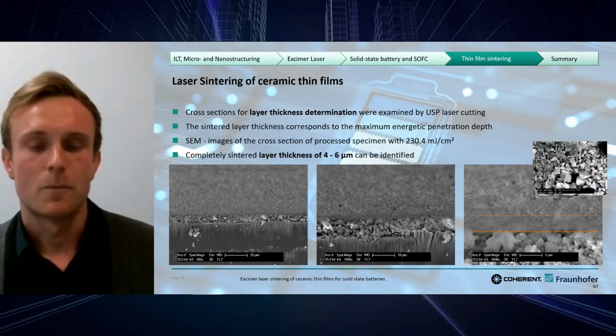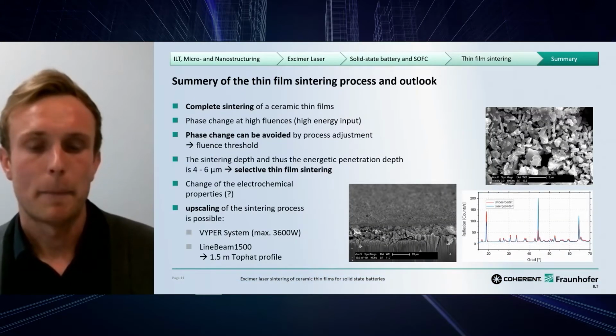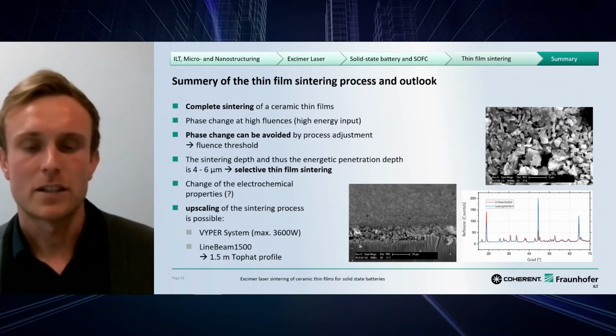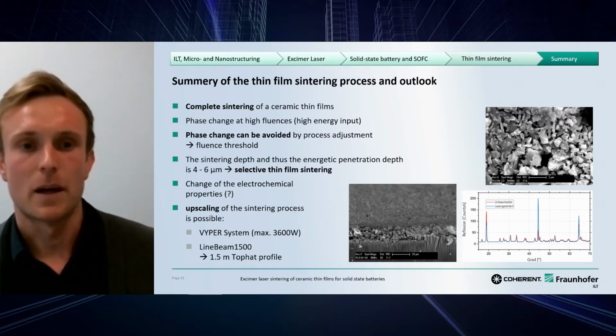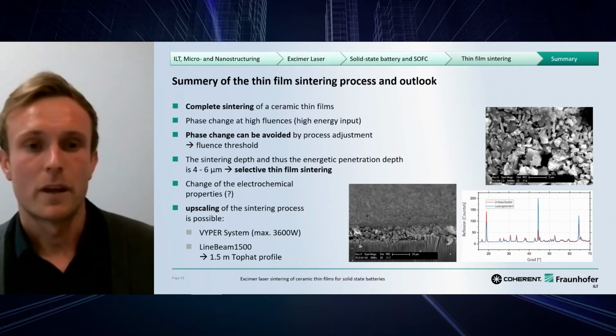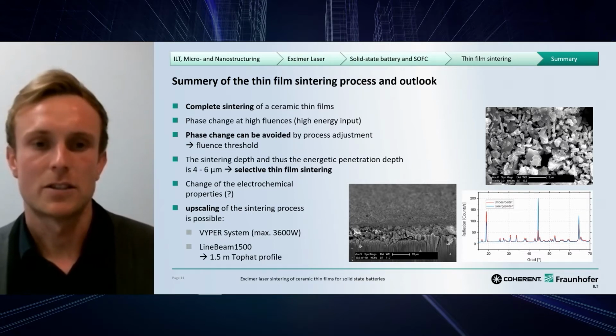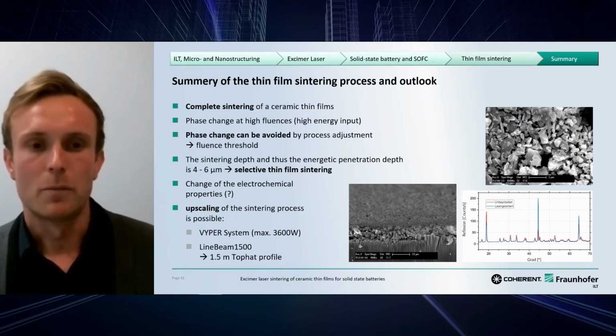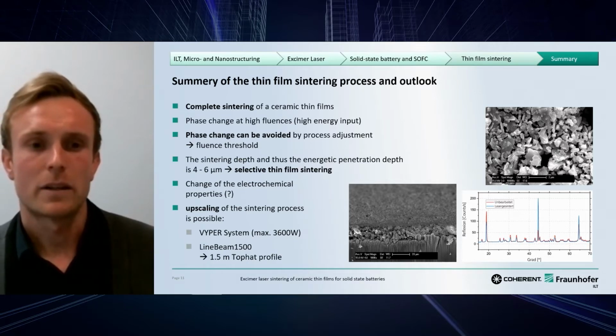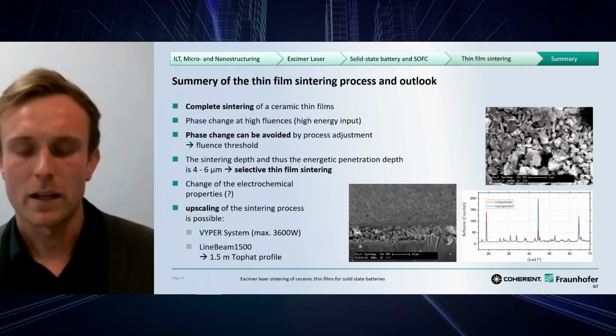With that, to sum up, we can say that the complete sintering of ceramic thin films is possible, that we have to stay beneath a fluence threshold to avoid a phase change, which can occur at higher fluences, and that we can precisely sinter these samples depth-selectively. Proof that the electrochemical properties are maintained has yet to be carried out, but I want to mention one other thing.